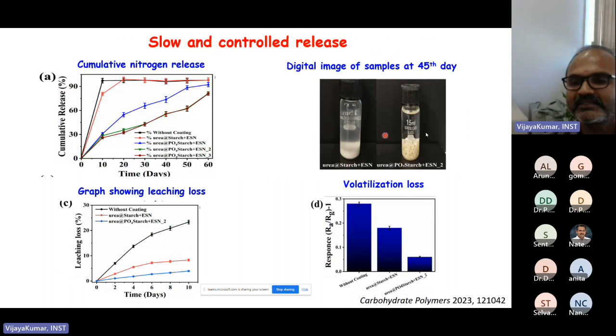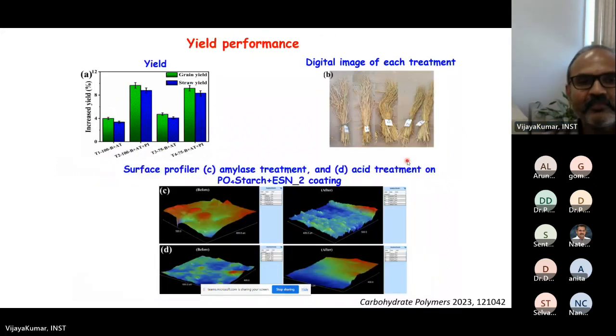And this is what happens after 45 days. Okay, it is just simple starch coating. You can see that there is a high stability. It is completely soaked in water for 45 days. There is no taking and keeping it back. Okay, so in 45 days we were able to see that the material is stable.